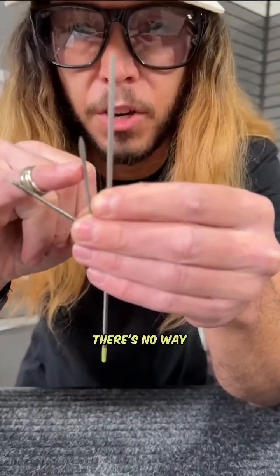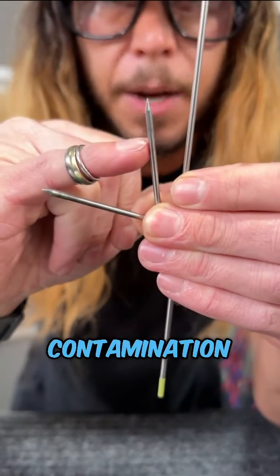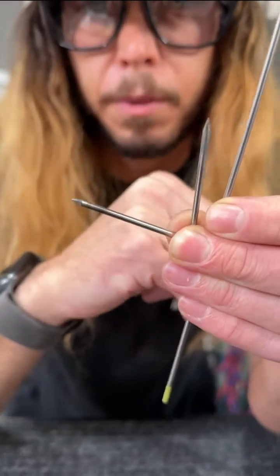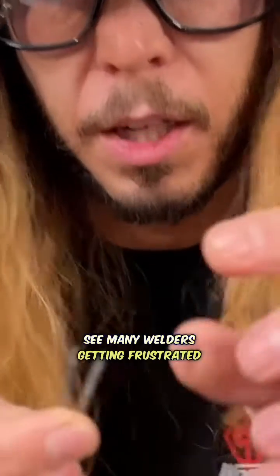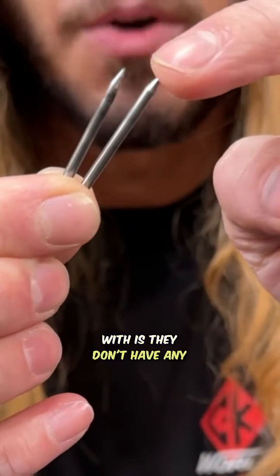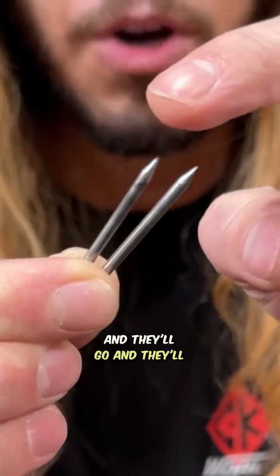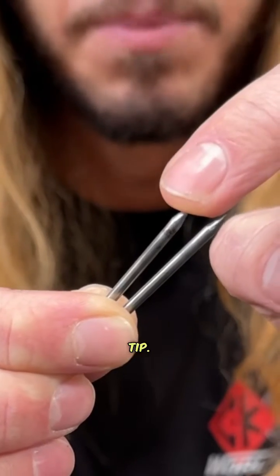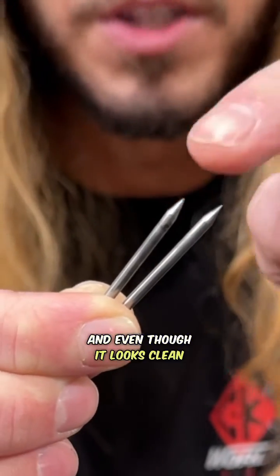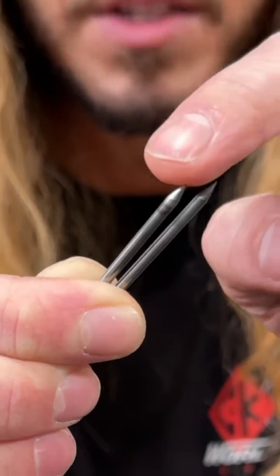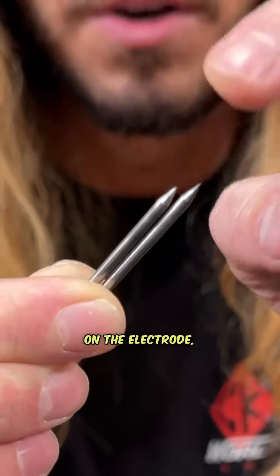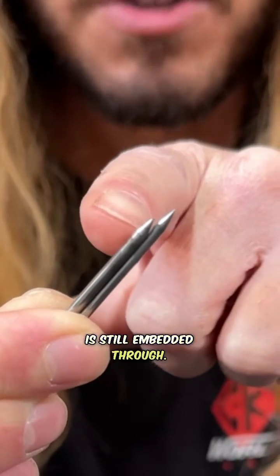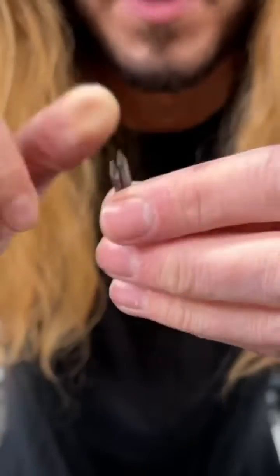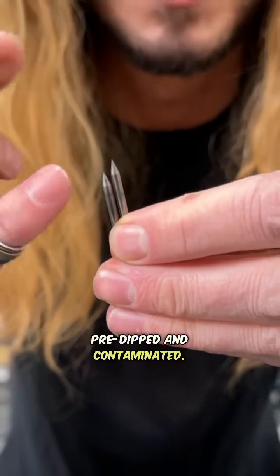Right here, there's no way to physically grind off that contamination because it's embedded throughout the tip. One of the biggest things I see many welders getting frustrated with is they don't have any arc stability, and they'll go and regrind this contaminated tip. Even though it looks clean and has a nice shaped point on the electrode, all this contamination is still embedded throughout. So when you light up that arc, essentially it is already pre-dipped and contaminated.